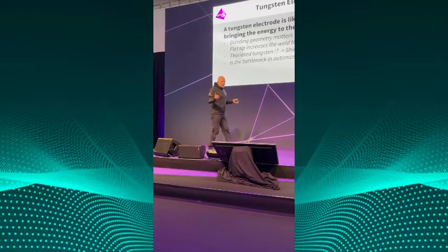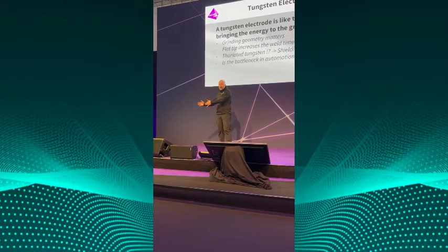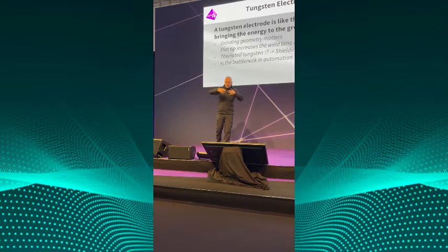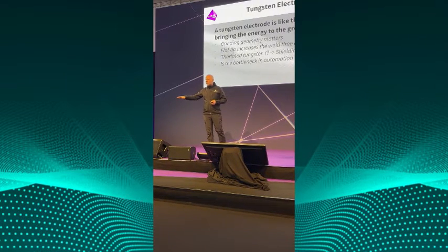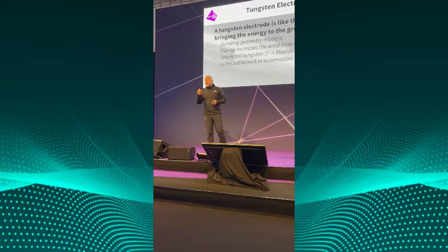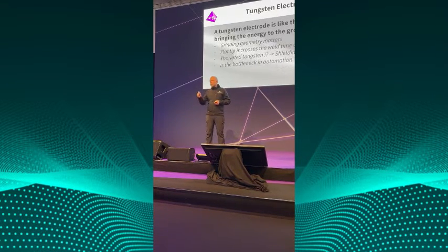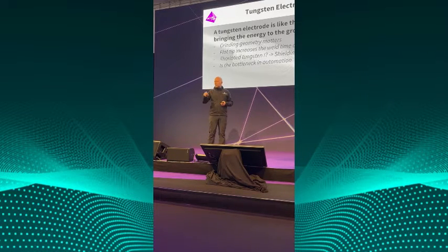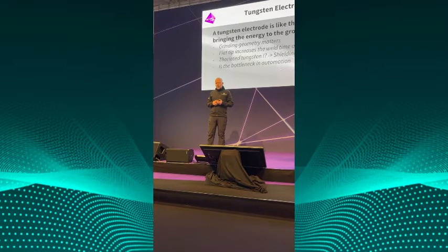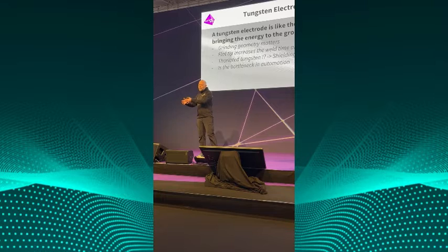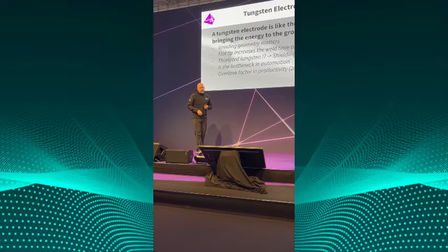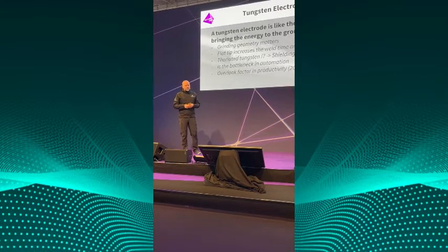It's the bottleneck in automation. You can buy a 100 kilogram wire spool, you can add a bottle assembly where you can weld a full month, but the tungsten electrode is almost always the first part which will fail. So this is the reason why you have to stop the process and you lose revenue. Often the mechanism is, because a part has a damage, you start to change the tungsten. So you should change the tungsten before you have production reject. And it's an overlooked factor in productivity.